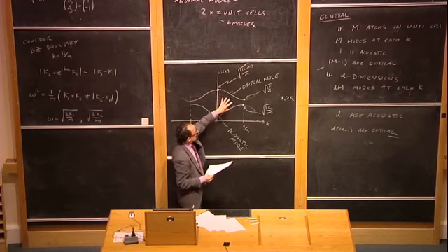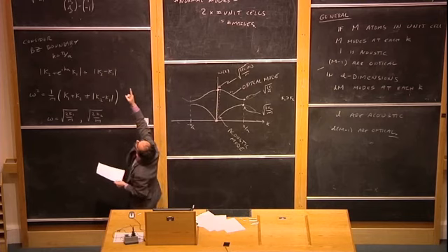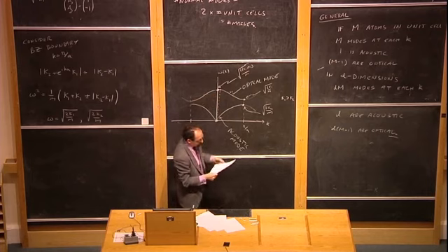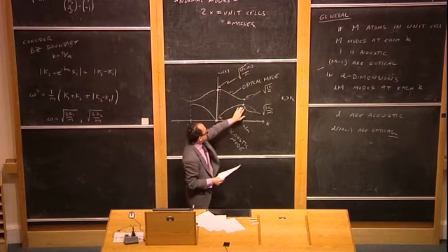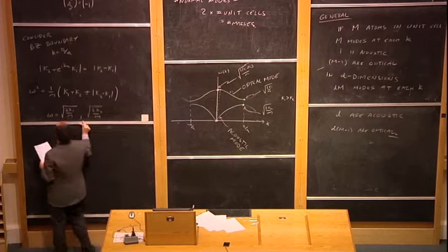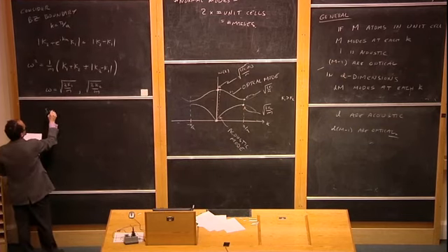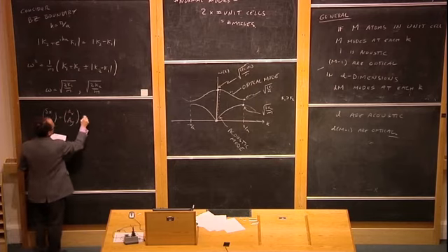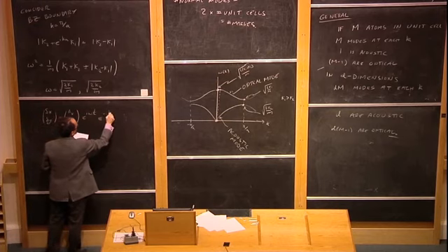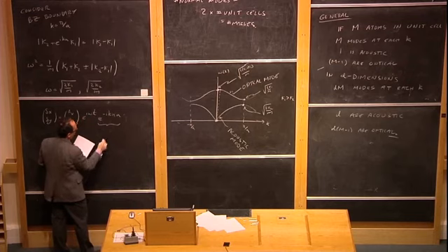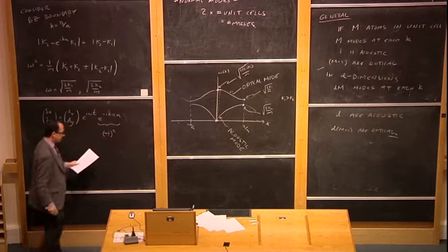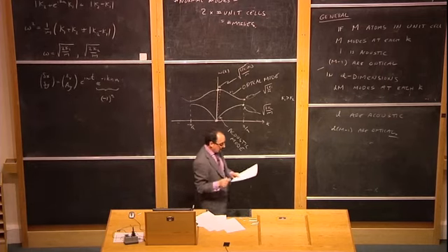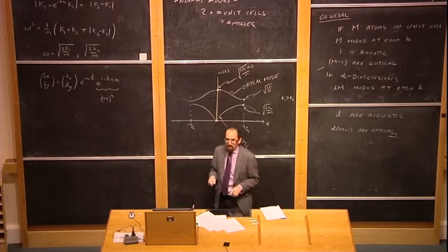And these modes actually never cross each other. You can convince yourself by looking at the form of the frequency. These two modes can never actually cross. So what's going on at this Brillouin zone boundary? At the Brillouin zone boundary, the waveform delta x, delta y equals a_x, a_y e to the i omega t e to the minus i k n a. This e to the minus i k n a becomes minus 1 to the n. And that tells us that alternate unit cells are moving out of phase with each other. They're moving in the opposite direction as each other.